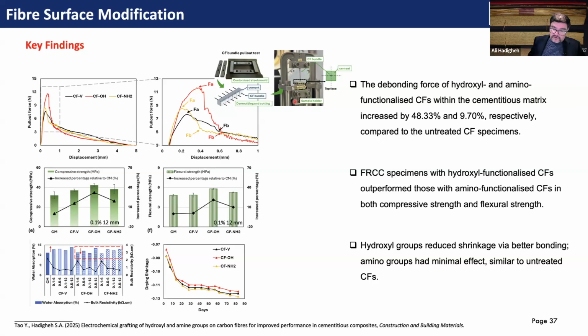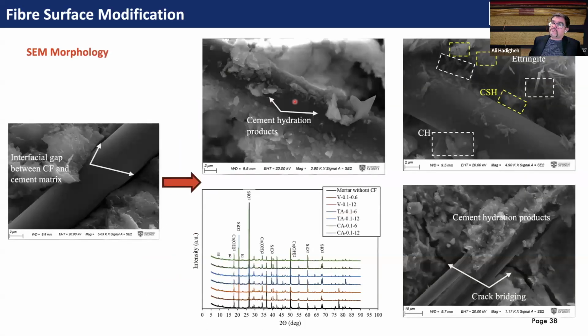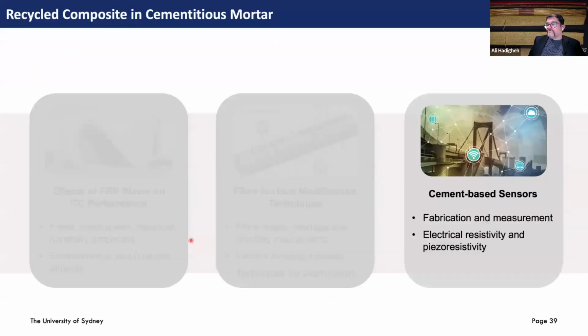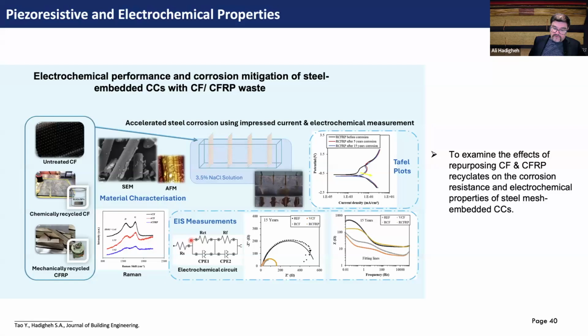And that was probably because of the hydration products and the interaction between hydration products and these functional groups on the fiber surface. And you can see this is simple carbon fiber, virgin carbon fiber without functionalization. But these are the functionalized carbon fibers. You see the interaction of CSH and carbon fiber, how well these are bonded to cementitious material. But the final area that we looked at was the electrochemical performance of these materials when we incorporate carbon fiber, for example, inside concrete.